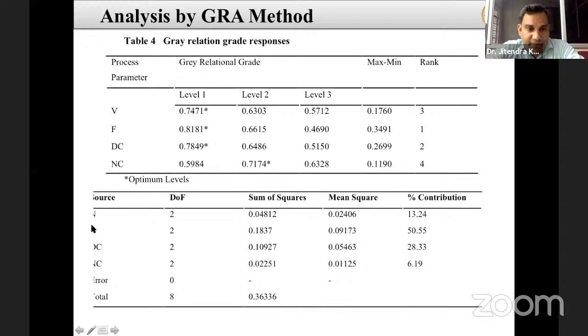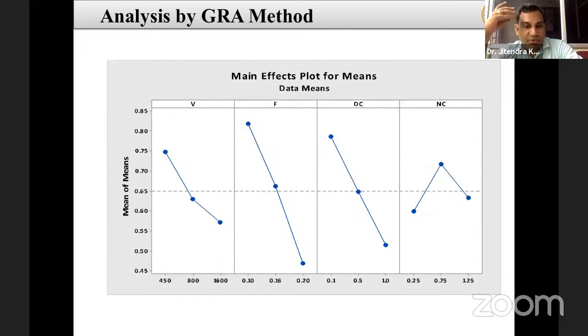So you have seen here the feed we have given to the tool to cut that particular material contributed 50.55, which means more or less 51%, then depth of cut, then cutting speed, and then nanoparticle concentration. These are the percentage contributions to the output parameters, which are the cutting forces and the surface roughness. So through this we analyze, going from maximum to minimum.